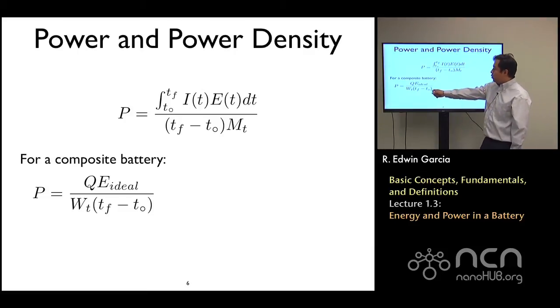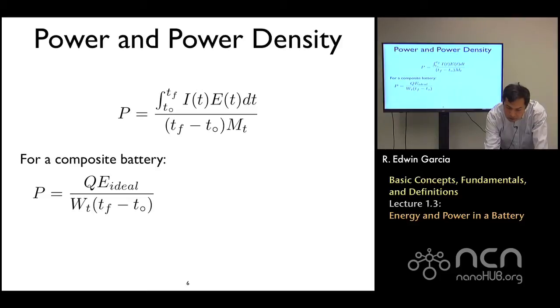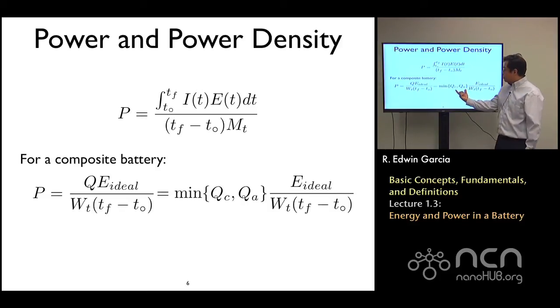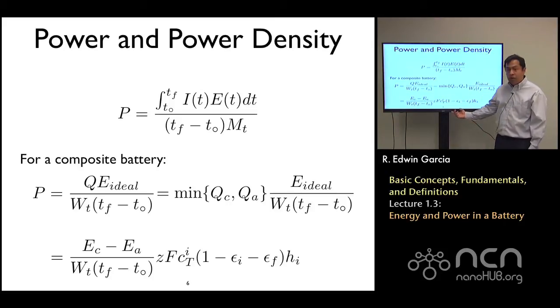We can relate that to the quantities we have defined by using the amount of charge that each of the electrodes can give us times the ideal voltage, that is the voltage drop. We will need to identify which of the two electrodes, most likely the cathode, will specify the limiting rate for storing amount of charge. This ideal voltage will correspond to the voltage difference between anode and cathode. We want the mass to be as small as possible in order to get the highest possible power associated with the system.